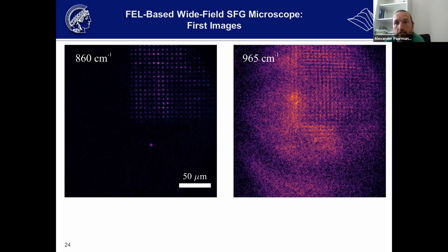So I don't see why not. That's clear. But you're limited to how much the phonon resonances shift if you look at phonons. If you don't have phonons, I don't know. I don't think, for strain in a metal film, you have a good contrast mechanism that will give you strain information. I think then it's much better to use other methods. I hope that also answered the question.